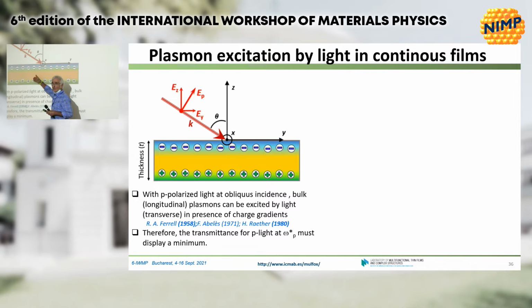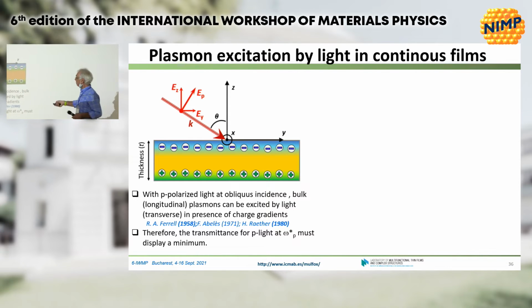If you have a film, whatever it is, a metallic film, and here I have depicted a possible excitation, a possible transverse plasmon moving in this direction, right? Light is coming here at some oblique angle. Now this light is polarized P, so it's in the plane of the screen. The polarization field is in the plane of the screen. It's going to have a vertical component and a horizontal component. The horizontal component is not going to excite anything here because the film is infinite. But the vertical component is going to excite this motion.